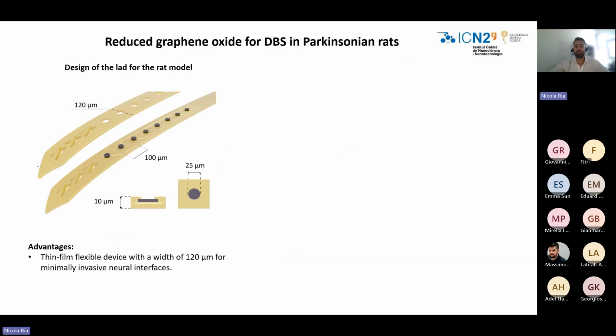So then the idea was to explore the potential benefit of reduced graphene oxide for deep brain stimulation in Parkinson's disease. And for this reason, we designed a lead for the rat model, so to conduct some experiments in the rats. And we designed a very compact lead of 120 micrometers in width and only 10 micrometers thick, with an array of 8 electrodes, so 25 micrometers. So this device is a thin film flexible device, is very compact and flexible, and this is very important for minimal invasive neural interfaces.